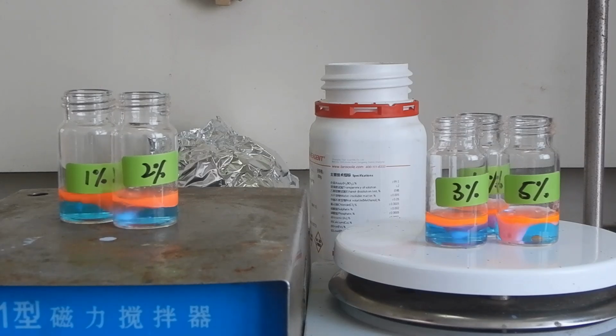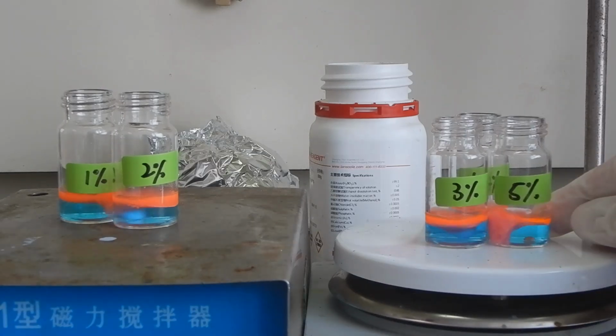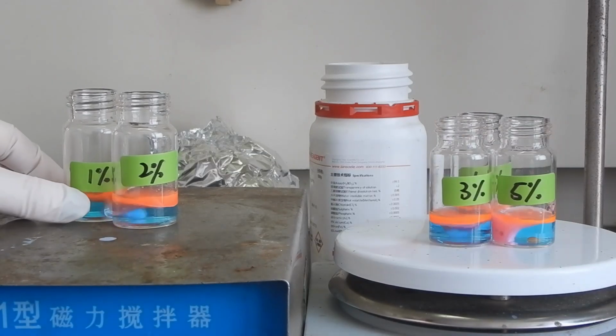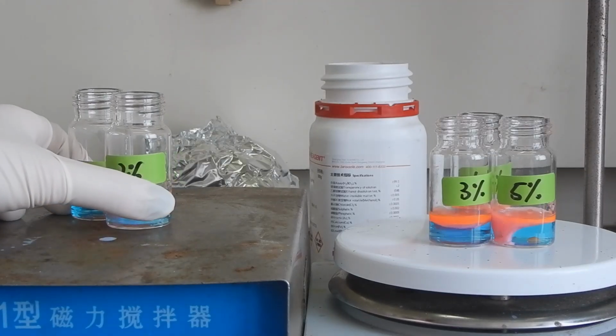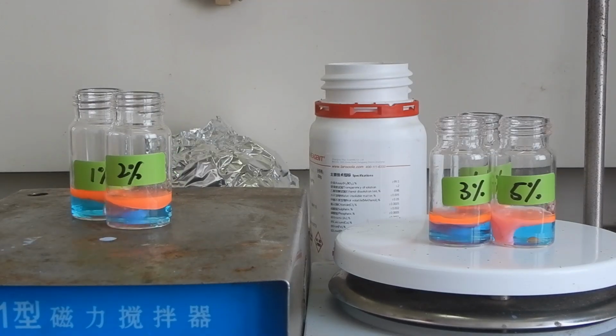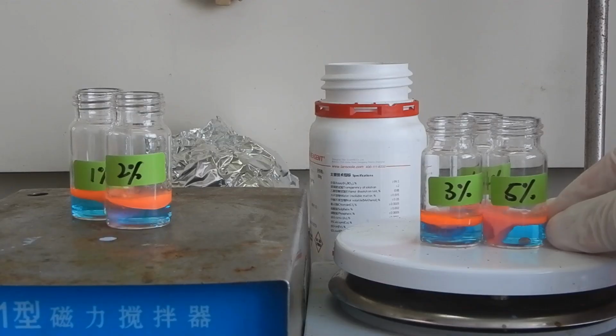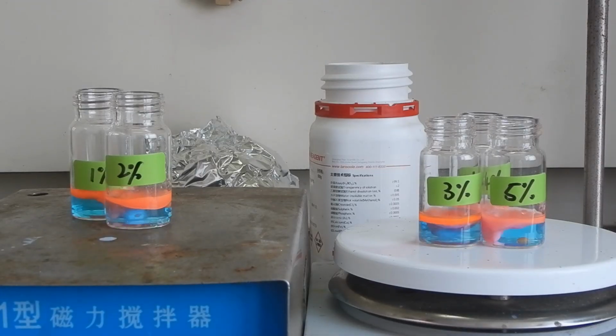of water. You can see clearly in this contact angle measurement photo that the modified DMSN-methyl has a far larger contact angle than the unmodified version, proving that it is indeed hydrophobic and thus capable of forming water and oil Pickering emulsions. The science with emulsions and interfaces will be explained in future videos, but for now, our hydrophobic nanoparticle is ready, and the only thing left is to install active catalytic sites.